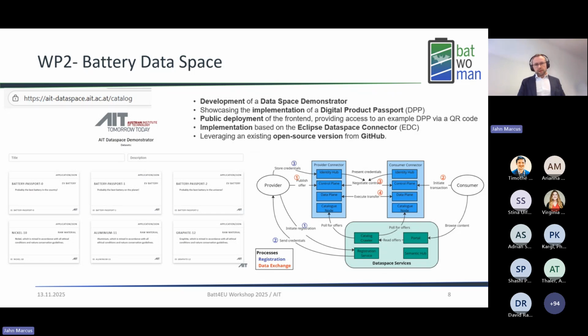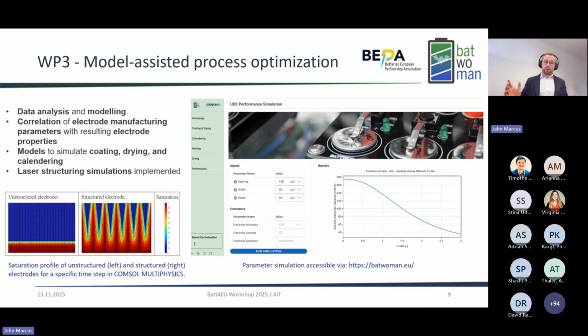Very similar for work package 3, where we looked into model assisted process optimization. We really looked into the data that we generated for some of the most critical process steps, so the coating, drying, calendaring, the wetting, the drying, and looked at how this correlates to the performance. What we really tried to do is to cut down on the experimentation side. So you can input a couple of parameters that are relevant for the step, and then you get a little bit of a predictive performance out of this.